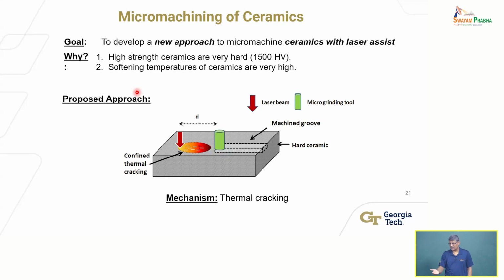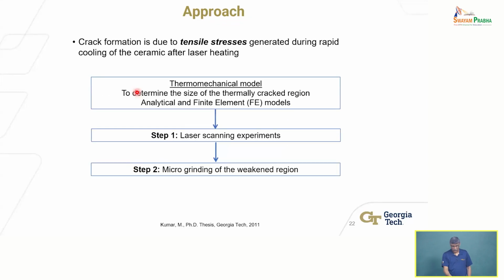That's my hypothesis, right? In the scientific method, we hypothesize based on our understanding. We present a hypothesis and we test the hypothesis. So that is our hypothesis. Can we do this? And indeed, is there a benefit, as I'm hypothesizing, in terms of lowering forces, etc.? So this is what we did. And so in this case, as I said, crack formation is due to tensile stresses generated during rapid cooling. It heats up and then it's cooled, and it's the tensile stresses generated during cooling, actually, after laser heating.